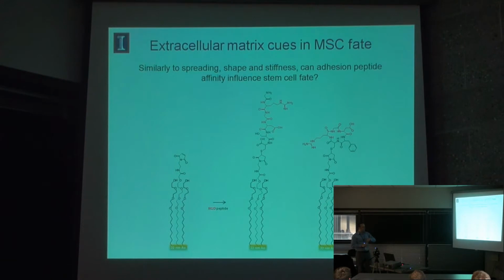And so to do that, we used our self-assembled monolayer chemistry, but this time using this maleimide functionalized monomer that we mixed into the SAM. And then we immobilized a thiolated peptide, one which has the RGD peptide, shown here in red, which is the linear peptide that's utilized in most biomaterials proof of principle studies. We also used the cyclic analog that had been explored for years as a therapeutic candidate.